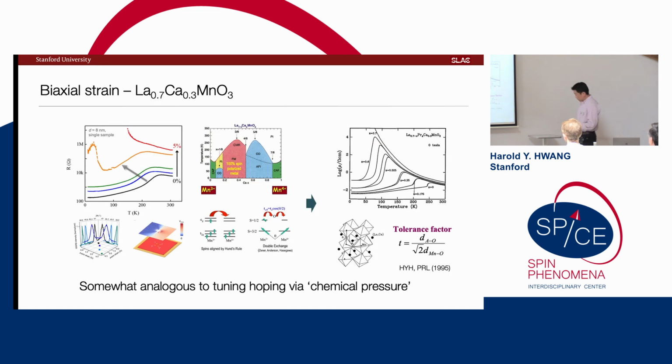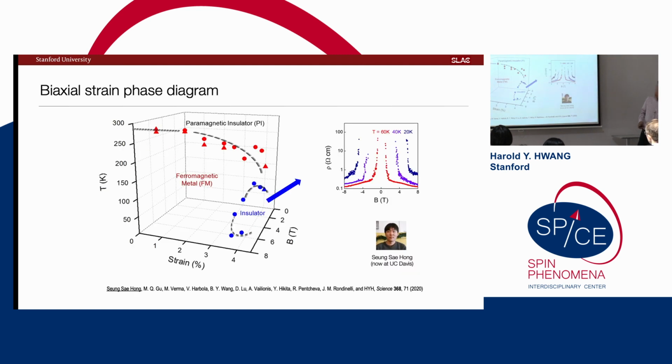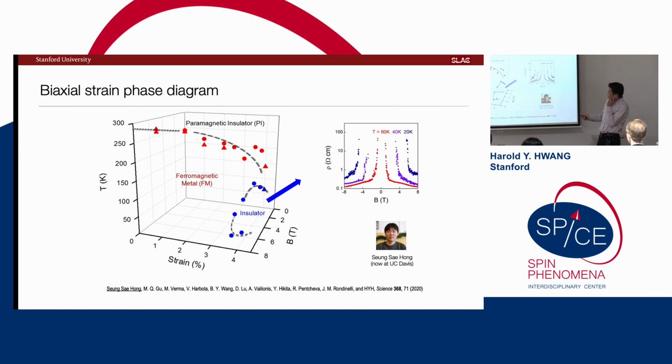This is a little bit older work, using a manganite membrane, taking advantage of the fact that we can make it very big and do uniform strain transport experiments. This is a biaxial strain geometry, where we could take the metal-insulator transition, suppress it, and go into an insulating state. One could then play with biaxial strain, magnetic field, and temperature, and explore quite a wide and interesting phase diagram where we can encounter magnetic transitions. We suspect that this insulator is an antiferromagnet, but we couldn't experimentally probe that yet.